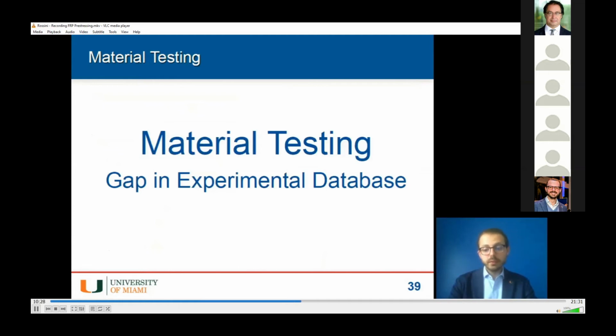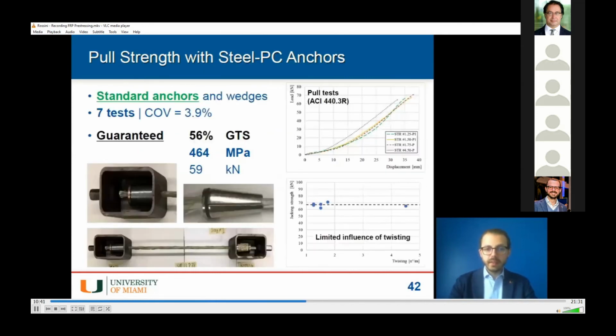But no one has ever tried to do this in the field, and not even in a laboratory, so we need to collect some experimental results, and we need to do our homework to see if this is actually feasible. Our experimental study focused on verifying if we can couple a traditional pre-stressing anchor used for steel strand with our prototype glass FRP strand. Here you can see how we grabbed our strand with traditional anchors, we pulled it, and we saw at which level of load it was breaking.